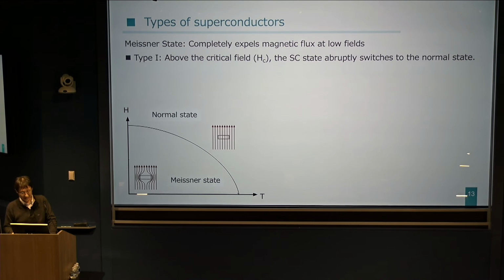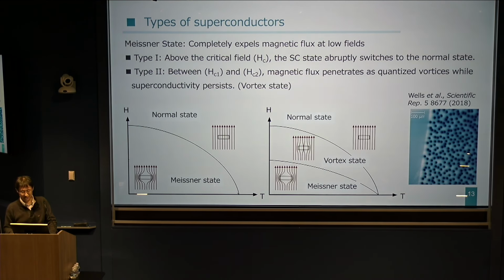But on the other hand, in the case of type 2 superconductors, the size of the Cooper pair is small, but the penetration depth is large. So the magnetic field has a chance to penetrate into the sample, and it makes the vortex. So in the case of type 2 superconductors, on top of the normal state and the Meissner state, between these two states, we have the so-called vortex state. And this is an experimental visualization of vortex.